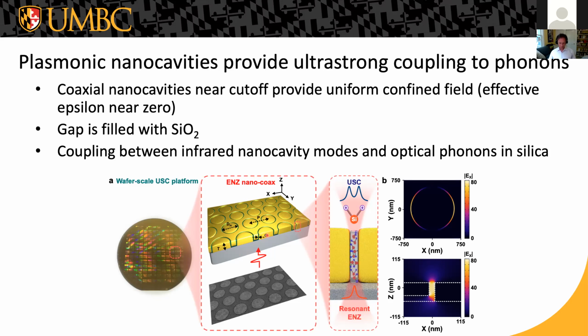And the film is not very long, so reflections at the top and bottom surface lead to Fabry-Perot resonances inside these coaxial cavities. And by operating near the cutoff of these coax waveguides, you can get highly uniform fields throughout the entire nanocavity. Right? If you look at it in terms of the effective mode index or the effective mode dielectric constant, these are operating in the epsilon near zero mode, where you get near zero phase shift and uniform fields throughout the entire cavity. So that any material inside the cavity, regardless of where it's located, is going to couple strongly to these localized nanocavity modes. In this case, the system that's coupling is the vibrational modes, the optical phonons inside the silicon dioxide that fills up this cavity.